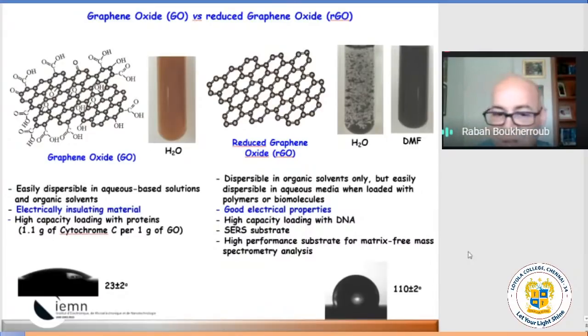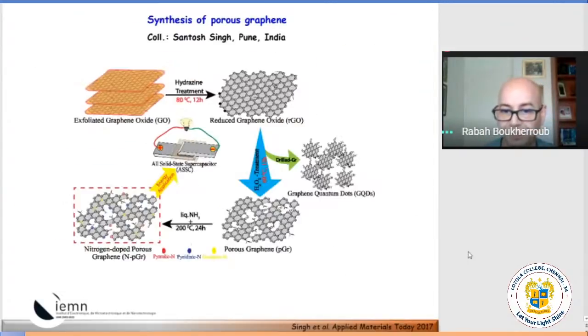As I said, you see, graphene oxide is very nicely dispersed in water. The dispersion is stable for months without any precipitation. And if you make a thin film out of this graphene oxide, you see it's hydrophilic. This contrasts with the reduced graphene oxide, which actually precipitates out of water, and you see it becomes black. It's because you have this aromatic and conjugated structure. However, you can easily process this in different organic solvents. So we can actually disperse it in THF or many other polar solvents.